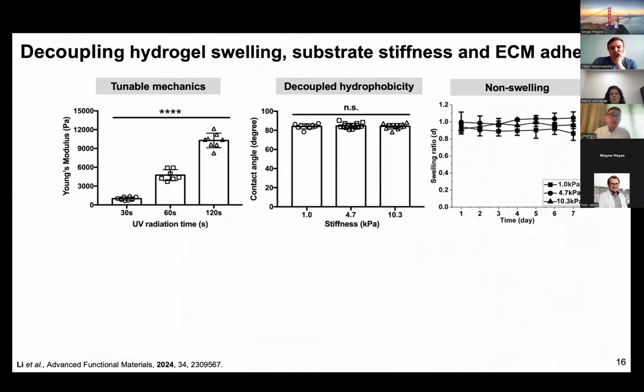morphologies as well. So this shows that we can change the different ECM proteins that we consider as biochemical signals. Now the next question: can we decouple the biochemical versus the biophysical properties? As we use UV to crosslink the hydrogel because it's radical polymerization, we're able to tune simply by the UV radiation time and control the stiffness, from 30 seconds to 120 seconds. We can achieve the lowest stiffness of 1,000 pascals and the highest about 10,000 pascals. So we can tune the mechanical properties.